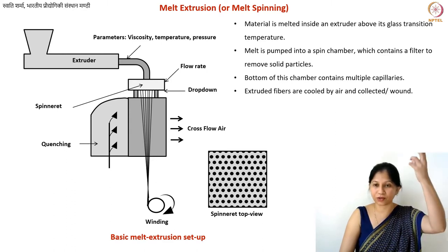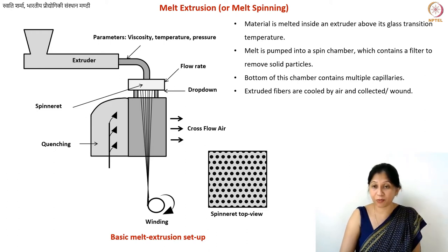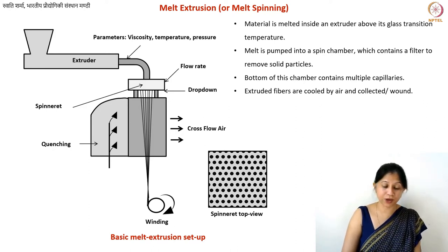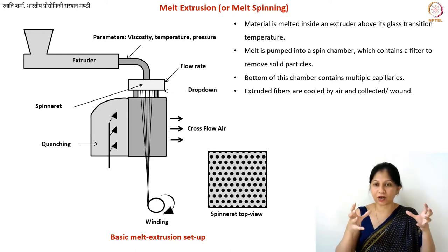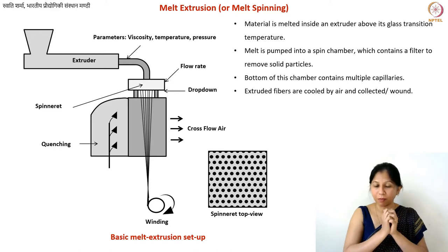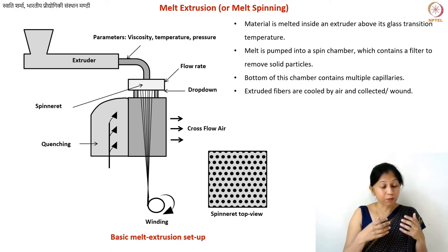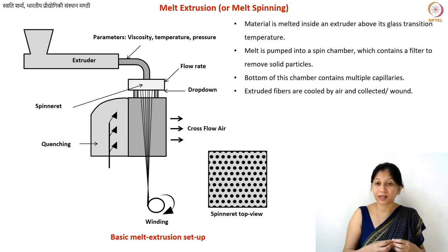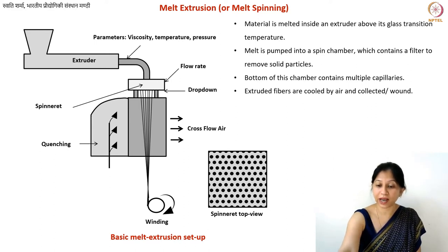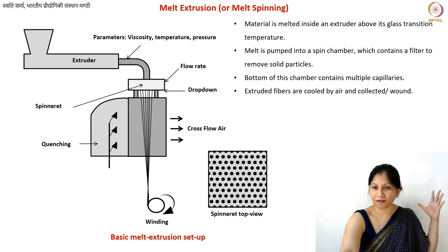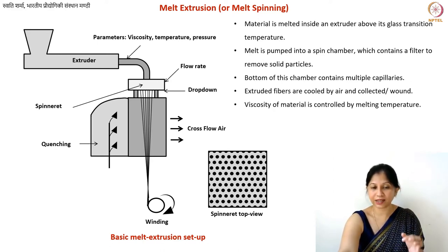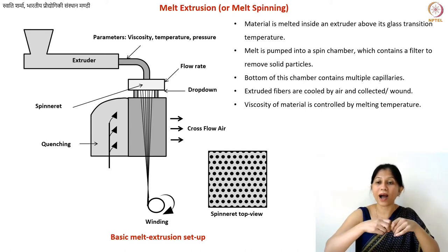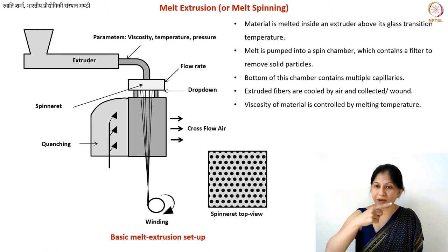You want to make the fibers glass-like and hard. You can do quenching or cooling by air — blowing air helps fibers stay apart and not agglomerate into one big chunk. This needs to be done very soon after they come out of the extruder. In industrial setups, you typically have a cross-flow of air for cooling. At the bottom, you have a fiber collection and winding unit, and as soon as the fibers dry you collect them. That is how melt spinning is performed.